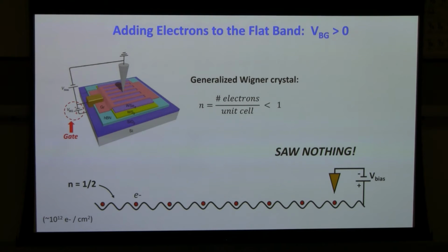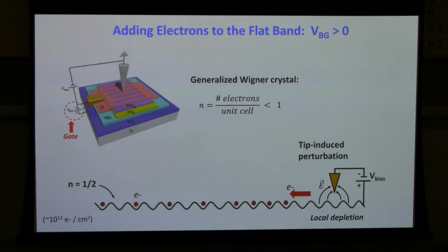The reason it didn't work is because of what's happening with the tip, to image with the STM tip, there are electrostatic charges. For example, if you bring 2 materials that have different work functions close to each other, there's going to be some charge transfer between them, and there's going to be some charge difference. And that charge difference is going to create electric fields.